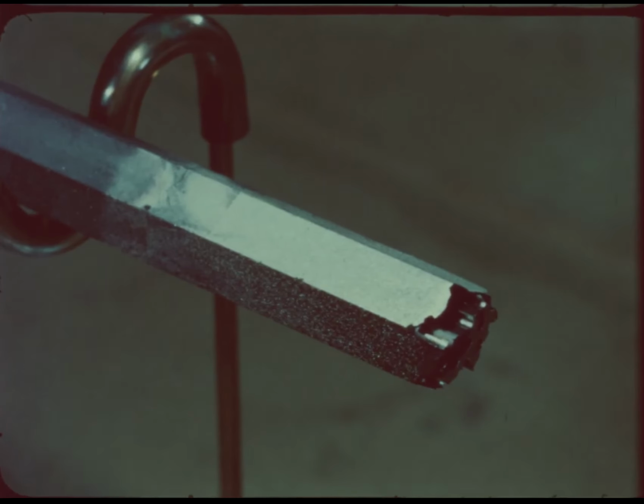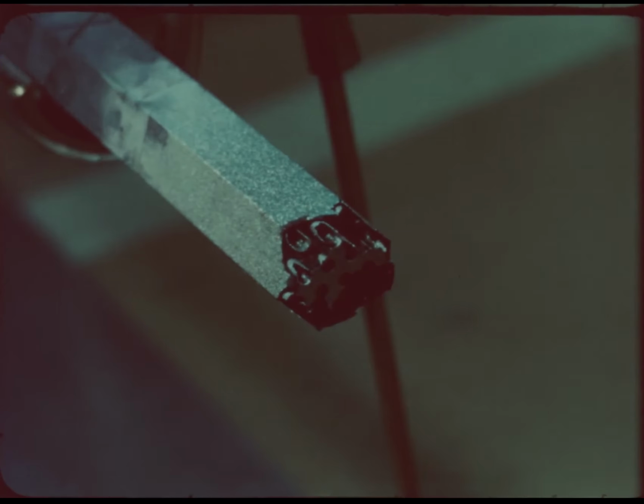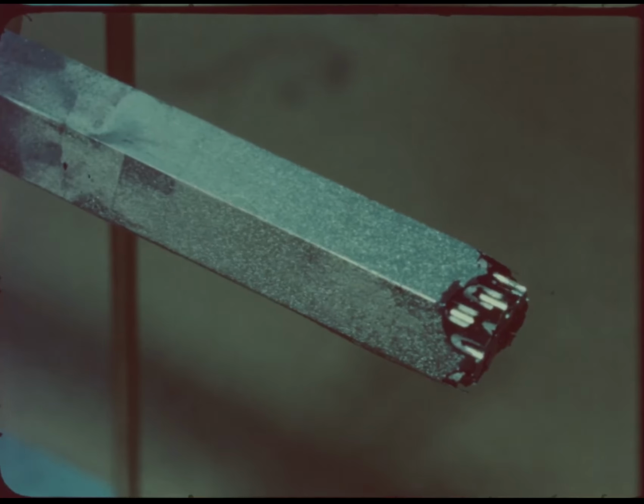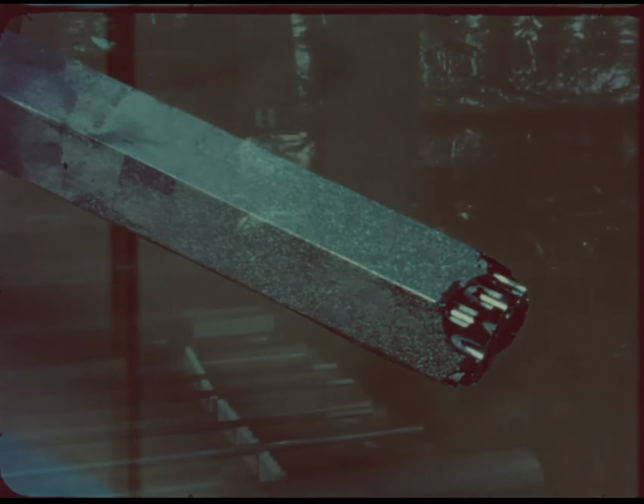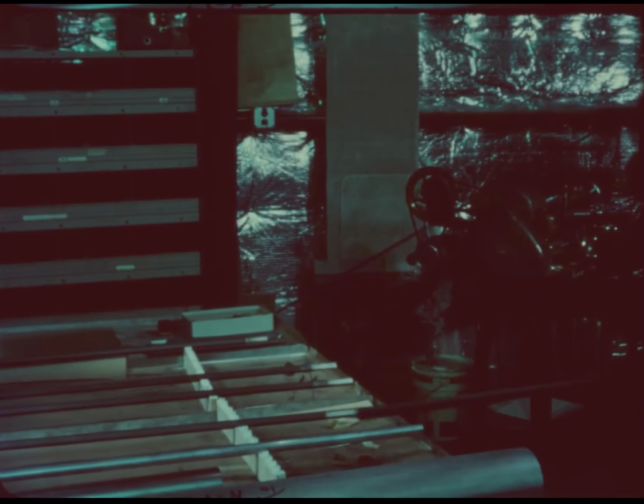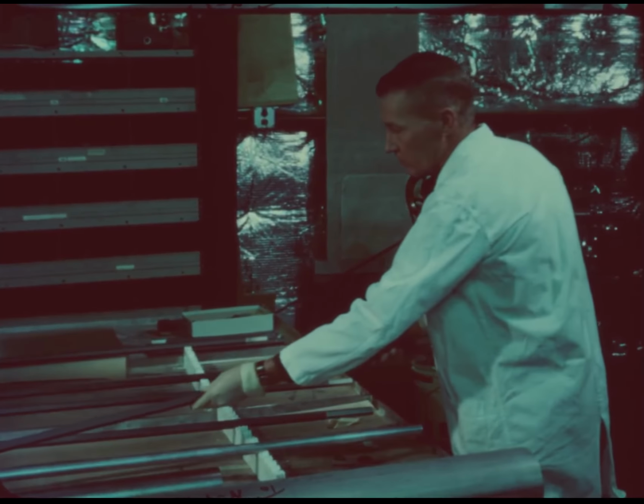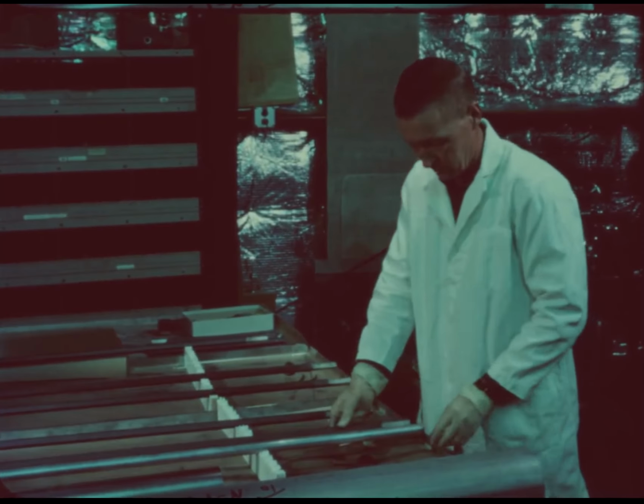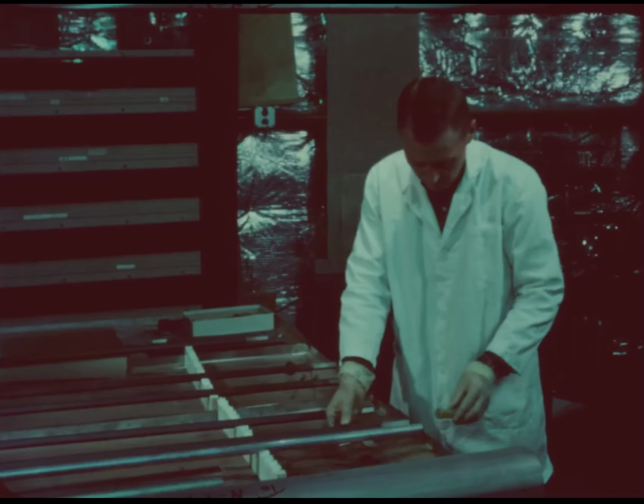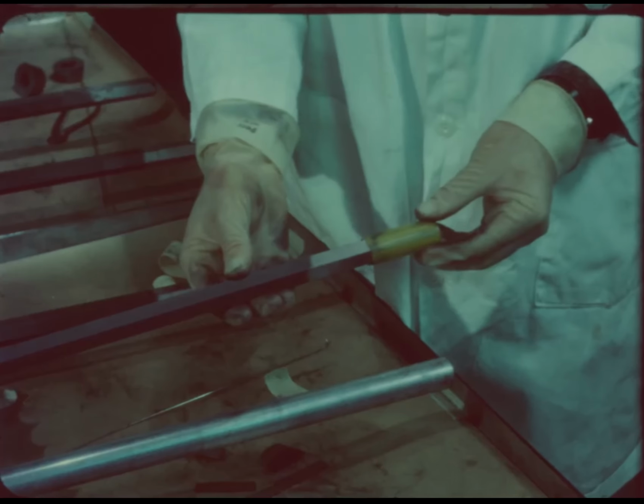The corrosion of graphite in these elements clearly illustrates the need for the niobium carbide coating and the obvious reason for rejection of elements and support blocks having damaged coatings. Because these experimental fuel elements are going to be handled many times, particular attention must be paid to the various operations that involve frequent handling of them.